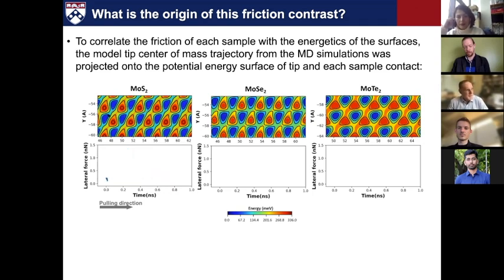I wonder, with the electrocatalytic activity, you would have additional effects from the different electron densities and electronic behavior and properties of these different materials. But it reminds me, there was something I meant to say and didn't say, which is that although we saw this friction trend with decreasing friction as we go to larger chalcogens, there is some simulation work from Clelia Righi's group in Modena, Italy, where she did simulations of not tip on layer, but layer on layer sliding. They looked at MoS2, MoSe2, and MoTe2 layer on layer. And they actually saw the opposite trend to what we saw. They saw that for the self-mated layer on layer interactions, they got higher friction as you go from sulfur to selenium to tellurium. And I believe that in their case,